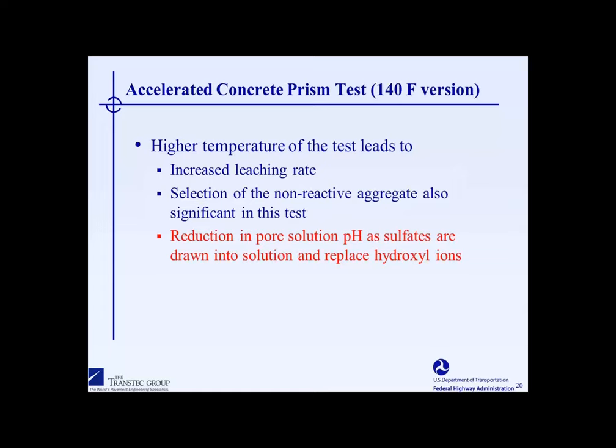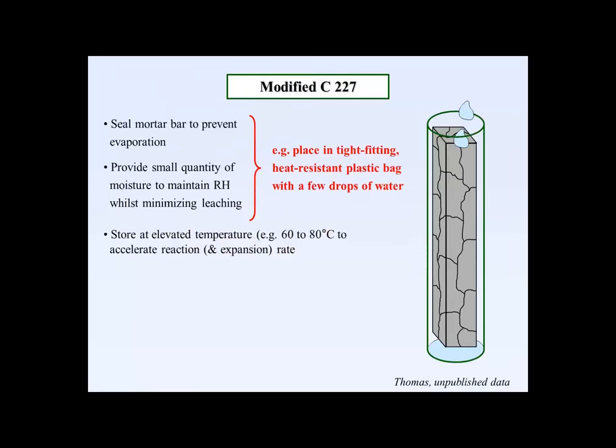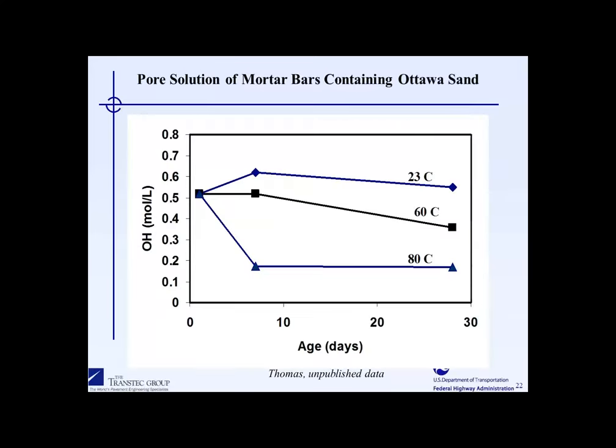Our index for pH is the hydroxyl content, and what you'll see is that the sulfates are replacing the hydroxyl ions, and therefore the aggregate's not reacting as much because it's not in as high of a pH environment as it was when we tested at 100 Fahrenheit. So let's look at some testing that was done a few years back, where the mortar specimens were cast and stored inside a tight container with just a little bit of excess water. Expansion was measured with time, and at various ages, the mortar bars were processed to remove the pore solution from them under high pressure, and then that pore solution was analyzed using chemical techniques.